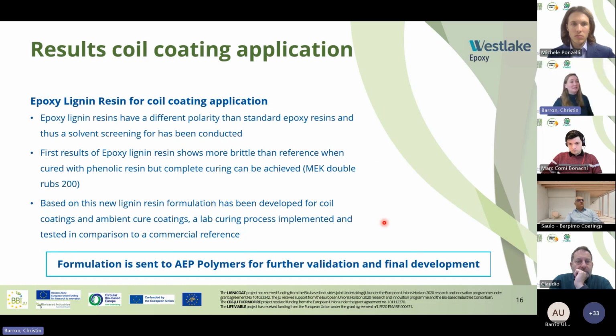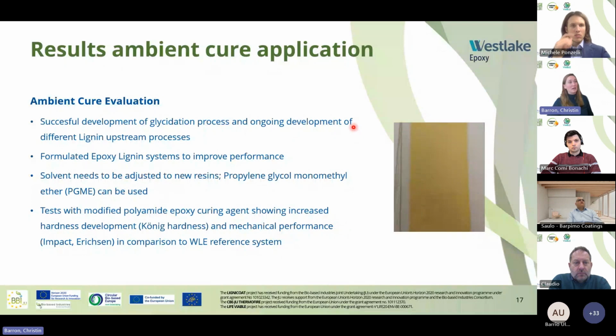And based on these new lignin resin formulations, we have been able to develop a coil coating formulation and also an ambient cure coating. A lab curing process can be implemented and also tested in comparison to a commercial reference. And these formulations that we produced are now sent to AEP Polymers for the further validation and the final development of these coil coating formulations. Our next goal was also to develop an ambient cure application. And based on the successful development of our glycidation process and also of our ongoing development with the different lignin upstream processes, we could start to formulate and to improve the performance.